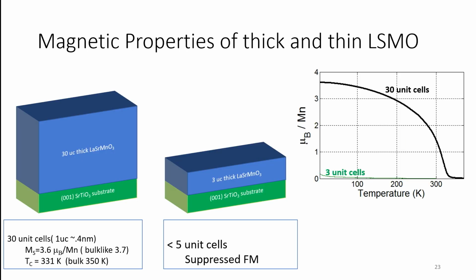So if you grow a 30 unit cell thick film, each unit cell is roughly 0.4 nanometers, so 30 unit cells is about 12 nanometers thick. You measure its magnetic properties in something called a SQUID. At high temperatures, there is no magnetic response because it's in that disordered magnetic phase. When you reduce the temperature, going down towards 2 Kelvin in this case, you can see that there's a magnetic moment that we can actually measure. And this saturates at a value which is very close to what you expect for bulk LSMO with this particular composition. So when you grow this material very thick, it behaves very much like the bulk, even though it's strained to the strontium titanate substrate.